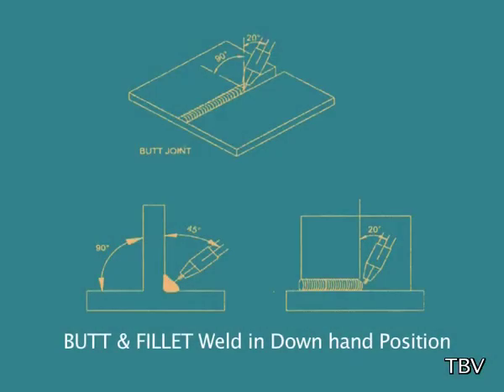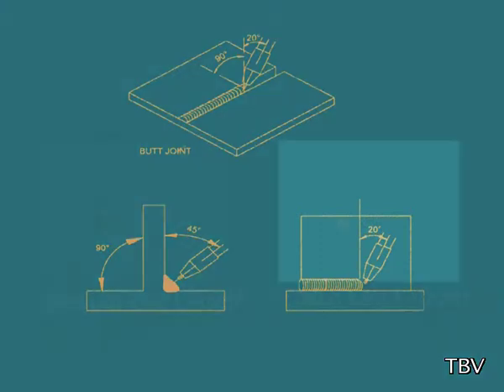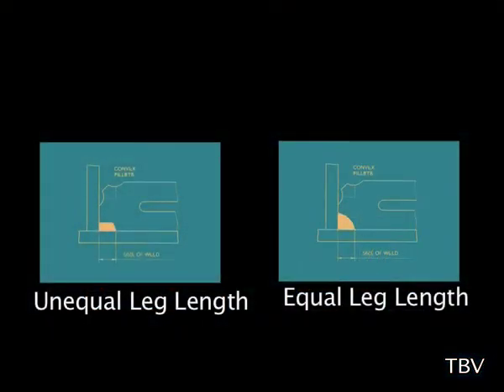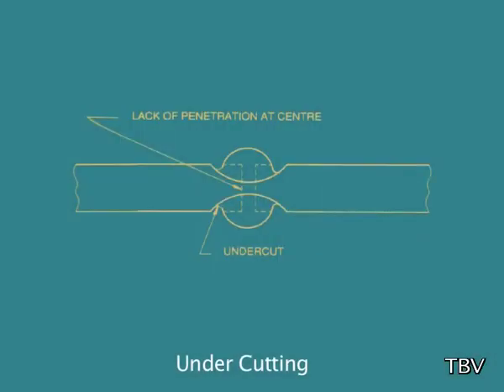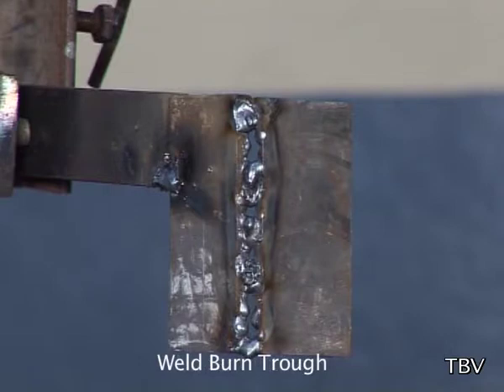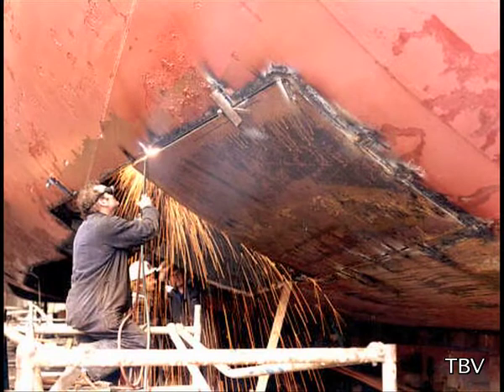Welding position. Spray type technique is restricted only to making butt and fillet welds in the downhand position. When used for horizontal fillet welds, this technique tends to give unequal leg lengths, convexities, and undercutting. For welding thin sheets in downhand position, spray type arc may give weld burn through. Vertical and overhead welding is usually carried out with short circuiting metal transfer.